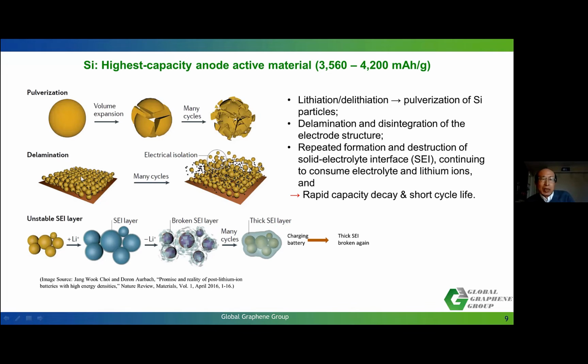Also, upon repeated deformation, volume expansion and shrinkage, the entire anode electrode can get disintegrated. That will also create a very severe problem. And if you make use of the liquid electrolyte, then there will be repeated formation and destruction of the so-called solid electrolyte interface, or SEI, that will consume your electrolyte and consume the lithium ions as well.